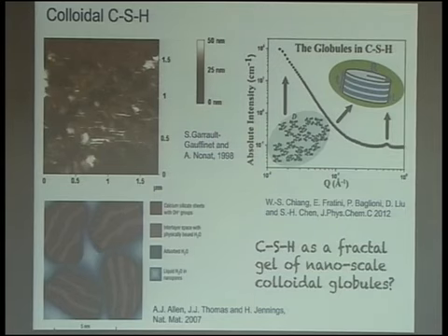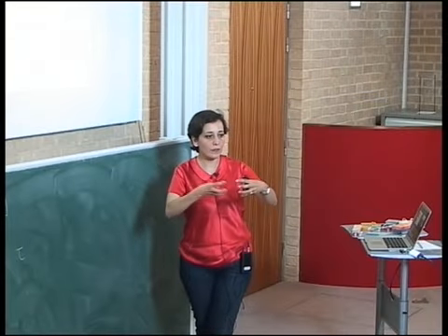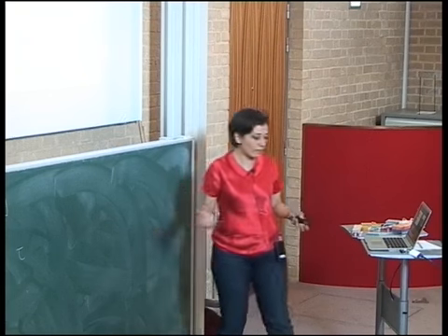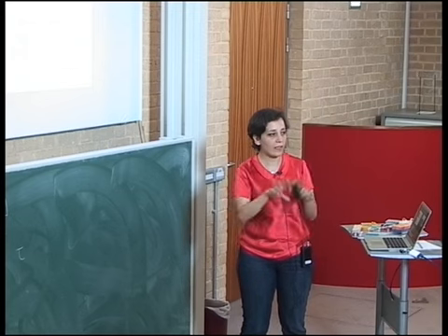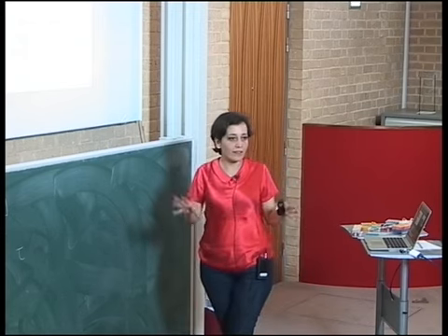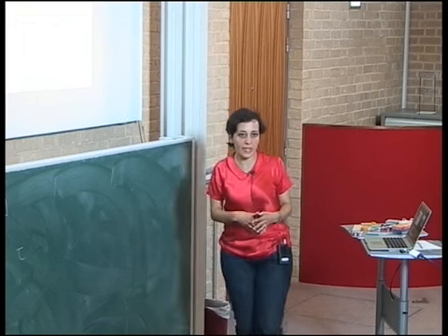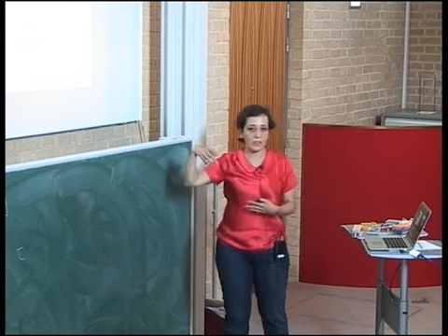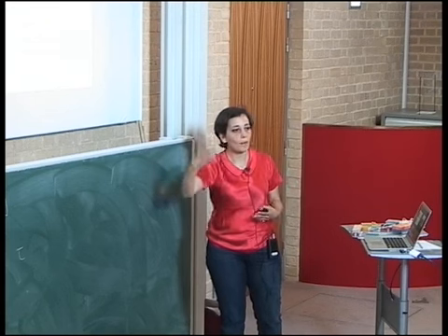What is clear is that this calcium silicate hydrate is organized into a complex structure in which you have layers of calcium and silicates that are interlaid with water, and then these form this type of colloidal units, let's call it like that, and then these units, which are typically 5 to 10 nanometers, organize into this more disordered structure. So people have come up, for example, with a picture in which you have a colloidal gel produced by sticking these particles together in the simplest organization that you would think for a colloidal system, that is a type of fractal gel. Although this is not very compatible with the fact that the system densifies enormously, so you cannot see any trace of this densification. And also what is difficult is to connect the features of this picture to this hallmark of the kinetics of the hydration.